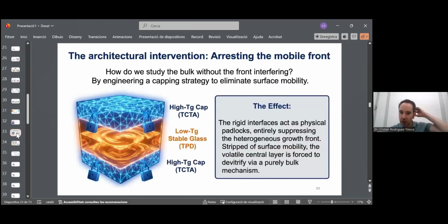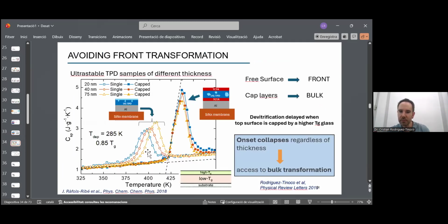Okay. Now, we said if we want to avoid this front transformation, we can just cap the surface, the interfaces. We freeze the surface, so we eliminate this higher mobility on the surface from the equation. Now we have only the bulk, so the glass can only transform via a bulk process. How can we know that we are effectively suppressing this front transformation? We can measure TPD, capped versus uncapped, the one we saw before, normalizing by the mass, and we see this apparent size effect, which, as I was saying, is not a size effect. This is a consequence of front transformation.